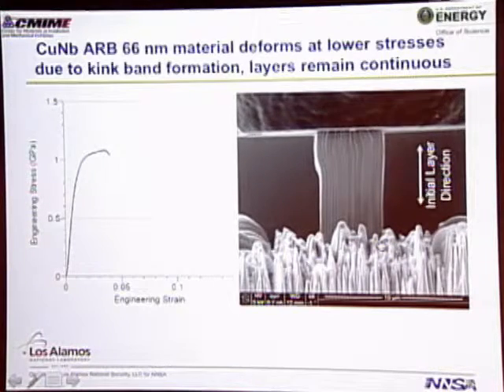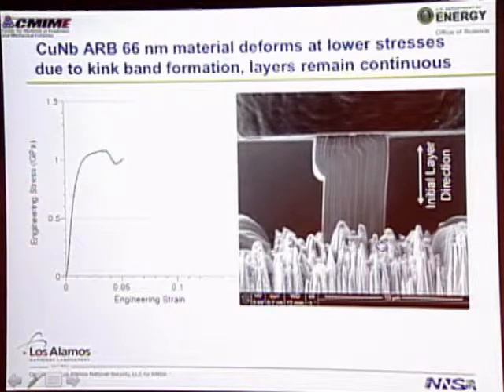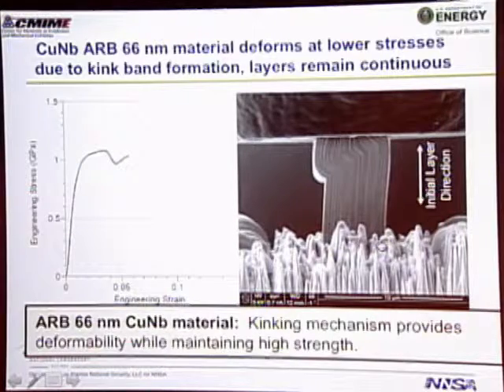If you can imagine this type of material, what happens is that we've got this very high strength here, still 1 gigapascal, but it can deform to very large strains a long way while maintaining that strength. It just kind of forms a kink band, gets a little bit weaker, and then hardens again. And so you can imagine that if you made an entire plate out of this material, it would absorb a huge amount of energy as you squash it.